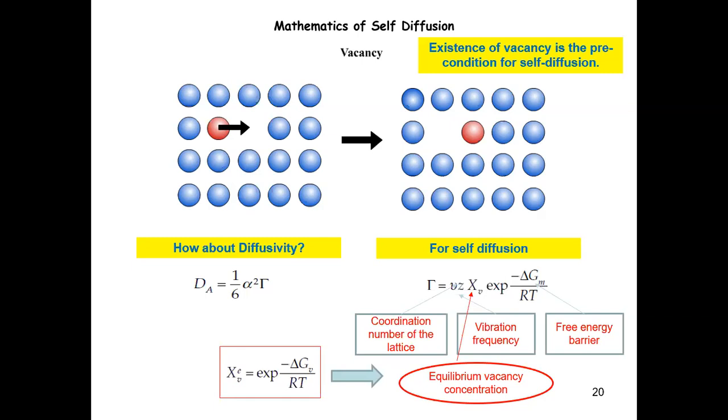So this is an interesting question. A way to answer it: whether these vacancies are equilibrium or non-equilibrium, what is the evidence to demonstrate this? I think the evidence is that these vacancies are observed at all temperatures above absolute zero, and their number increases with temperature, and they're stable. If these were non-equilibrium things, then you keep the temperature high, and these vacancies should go away. Does that make sense to everyone?